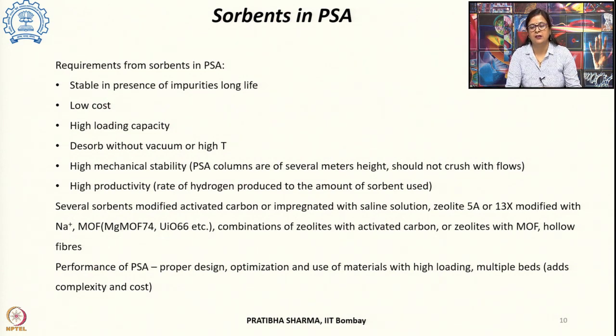Other than conventional adsorbents, there are modified adsorbents that can be used: modified activated carbon impregnated with saline solution, zeolite 5A or zeolite 13X modified with sodium ions, or metal-organic frameworks like MgMOF-74 or UiO-66. Combinations of zeolite with activated carbon, zeolites with metal-organic frameworks, or hollow fibres can also be used. The performance of PSA depends upon the adsorbent used, loading percentage, design optimization of adsorbent layers, and addition of multiple beds.